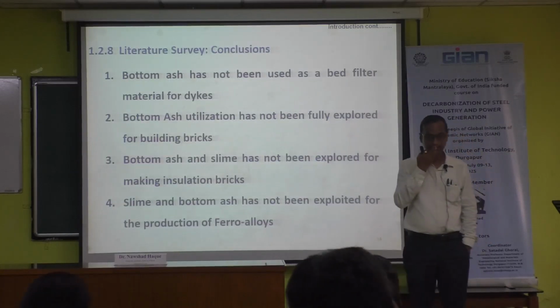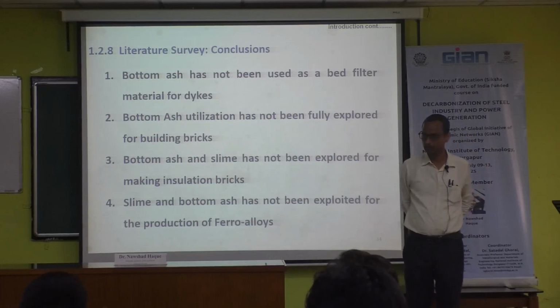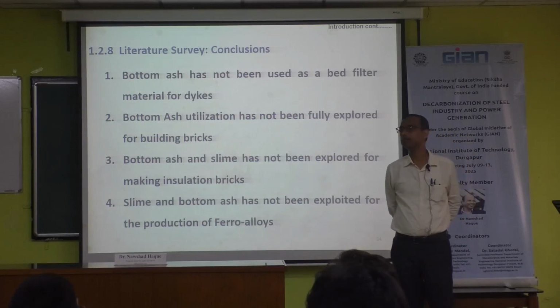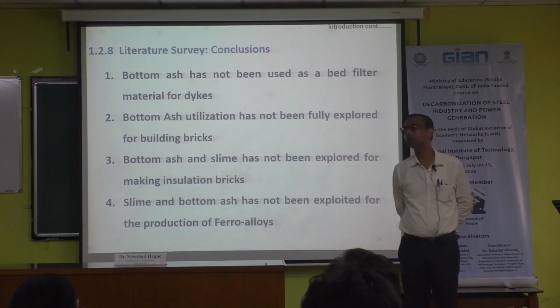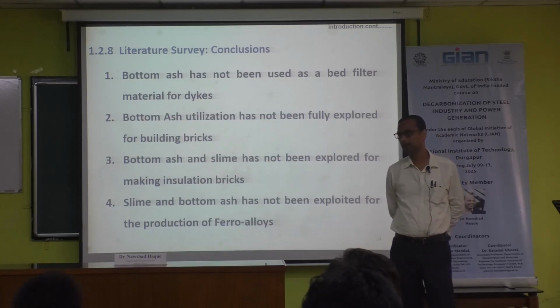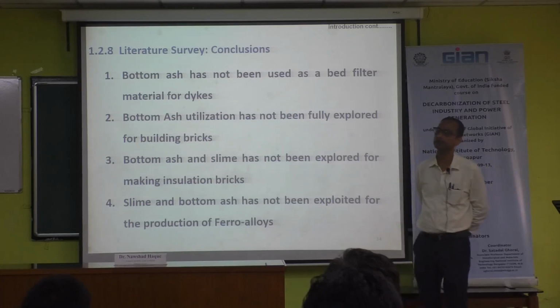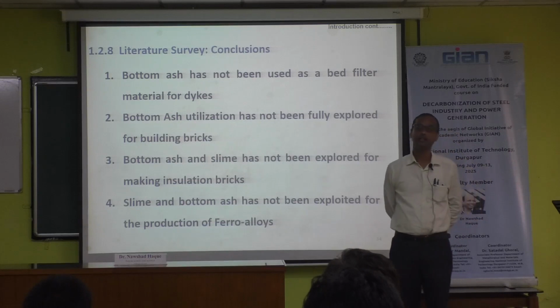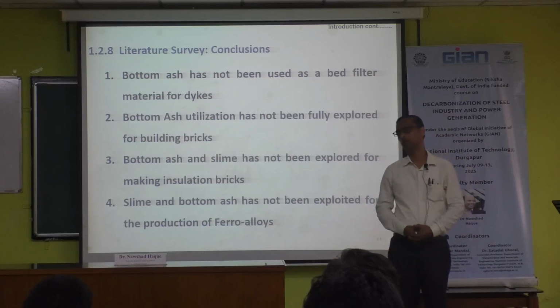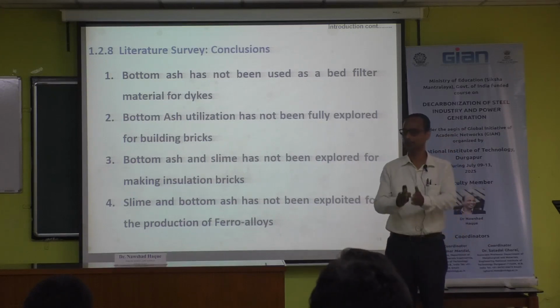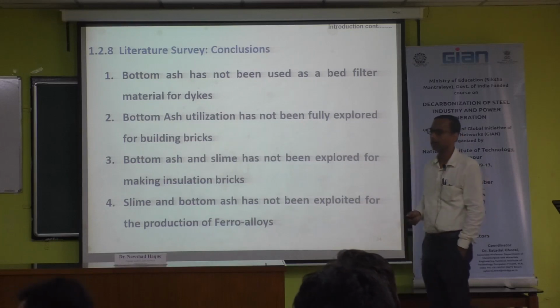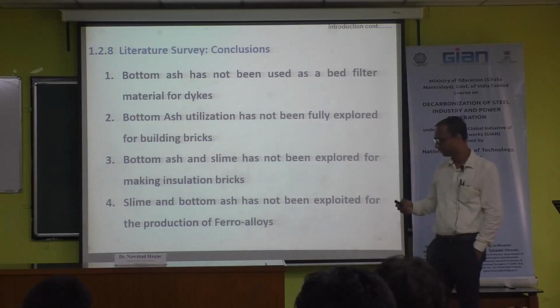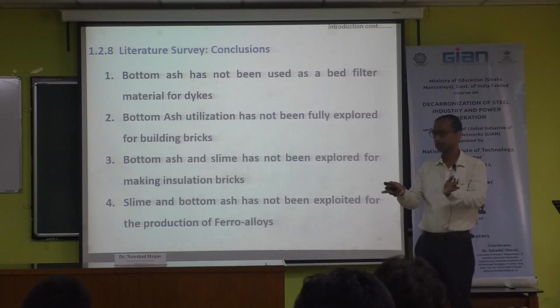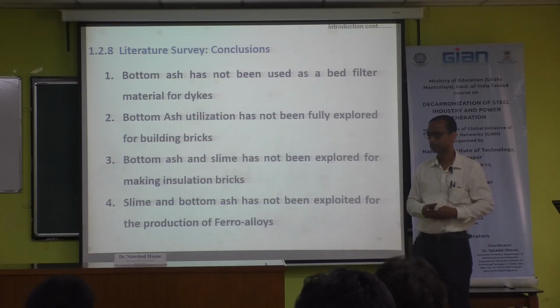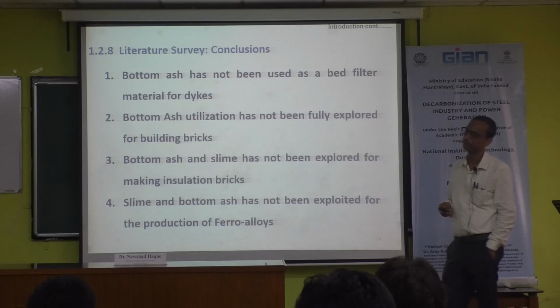At that time I talked to the plant guys also. Why is the utilization of bottom ash less? If you see the generation, can anybody tell me how much bottom ash there is? It varies, 10 to 25%, on average 10 to 25%. Therefore, they told me actually we dumped it in a single ash pond because the quantity is less, therefore we do not segregate. Now I think you have a separate area. We have dry bottom ash, so it goes into the silo, and is taken away for different landfilling and elsewhere.